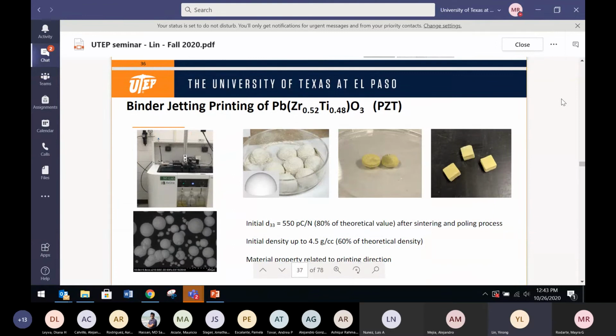All right, so the other thing we did is we're looking at particle size control, because one of the things for powder bed, how do you make a good powder bed, is very important. That's probably the most important factor in terms of controlling the final property, right? So most of the time you have to use spherical particles. You have to use bimodal particle size distribution to give you high density of powder bed, right? So we're studying that to print PZT, which is the most widely used piezoelectric material out there. And we showed we can get about 80% of the theoretical value by using this morphology control.